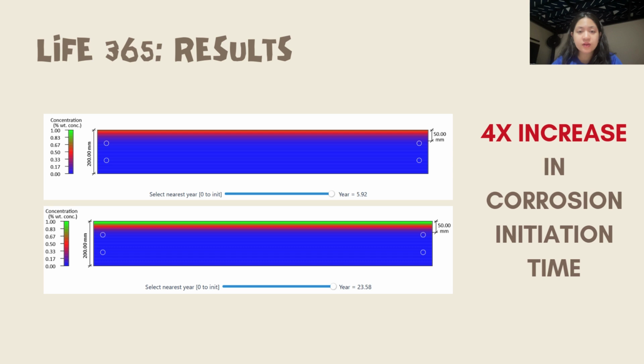This graph plots the percentage weight concentration of chlorides at 50 mm depth over time. For the base case, the threshold concentration is reached just before year 6. In contrast, the alternative case delays the same threshold until year 23.6. This delay in initiation time is crucial because it defines the first major phase of service life, which is to delay the onset of corrosion, as it ensures durability and mix optimization.